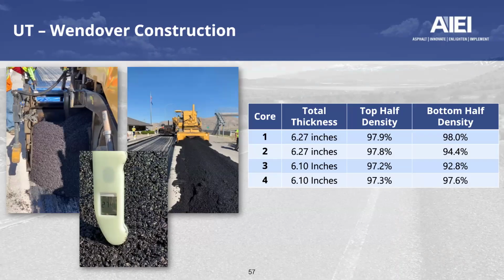All of the top half, the top 3 inches, were above 97%, approaching 98% on a couple of the cores. But also notice that the bottom half densities were generally high on cores 1 and 4, but in cores 2 and most notably in core 3, we see a downturn in density on that lower half. And the question is often asked, well, any idea what happened there? Well, I mentioned that you need to have your trucking on the A game.